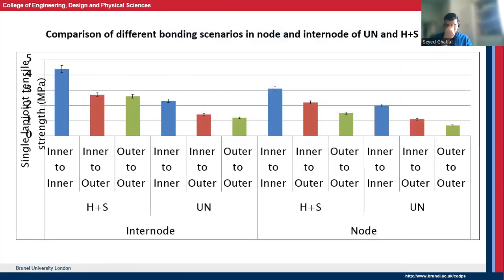Then we looked at the comparison of different bonding scenarios: inner to inner surface of the wheat straw, inner to outer surface, outer to outer, and inner to inner for the untreated straw, inner to outer and outer to outer. And you can see that the best performance comes from the inner to inner connection of the hot water followed by steam pretreatment of the internode, around 5 MPa of single joint lap shear in tension.